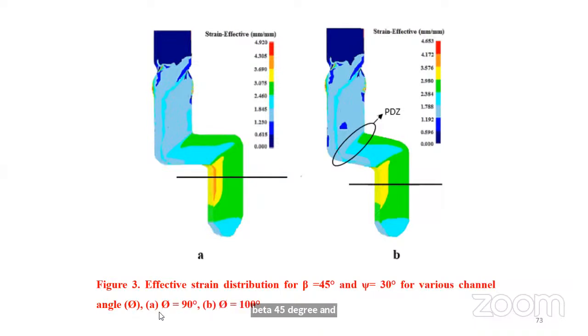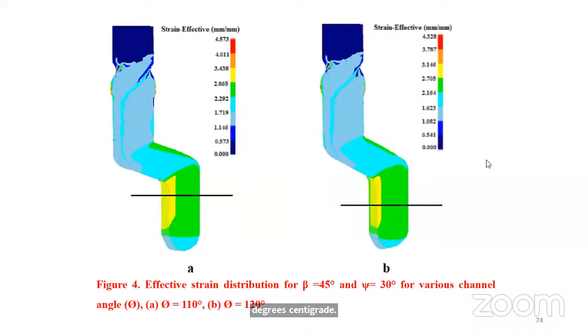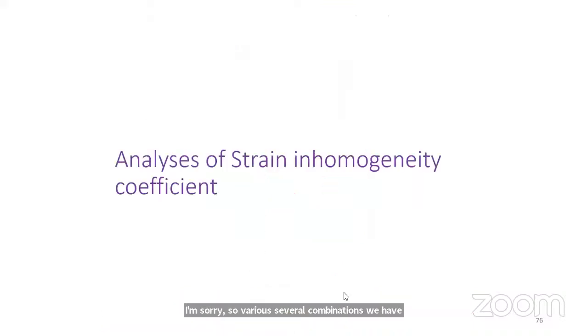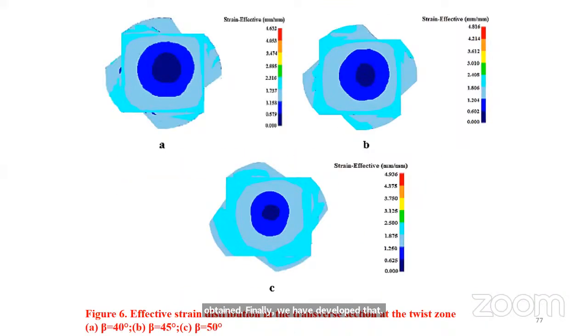Then the effective strain distribution taking beta of 45 degrees and corner angle of 30 degrees, keeping the channel angle at 90 and 100 degrees, we can see the effective strain achieved is 4.6. The 90 degree channel angle gives us more effective strain. The similar trend is attained for beta of 45 degrees and the psi angle. So we have obtained several combinations, and finally we have developed a die. With the strain inhomogeneity also, this is the strain inhomogeneity diagram. Effective strain inhomogeneity is in the transverse direction of the twist zone when beta is 40 degrees, 45 degrees, and 50 degrees.